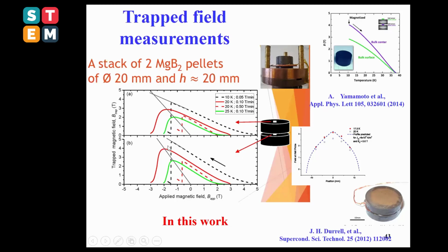But this value obtained can be compared with some reported data, where at 20K, by stacking again both samples, some colleagues were able to trap around 3 Tesla here. When you are here around 20K, you should be able to deduce in both conditions here roughly again 3 Tesla. That means the result you obtain is quite comparable to some reported data.